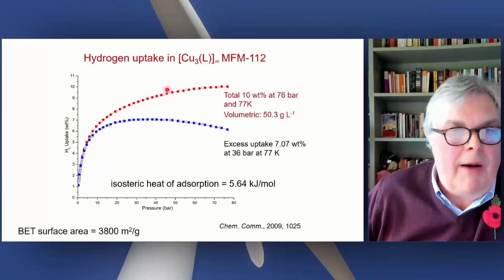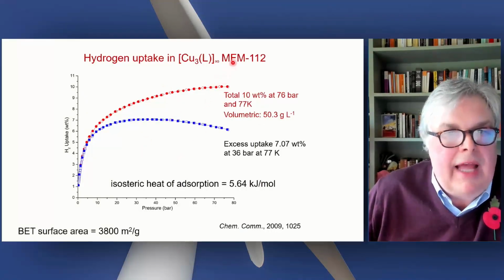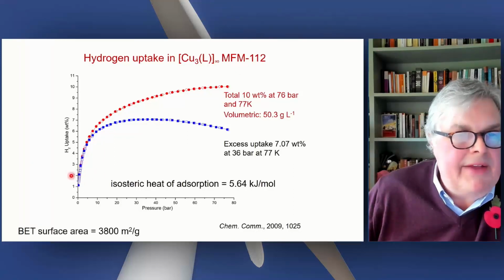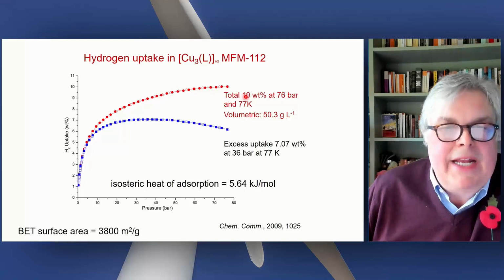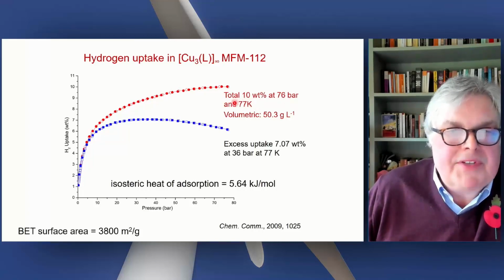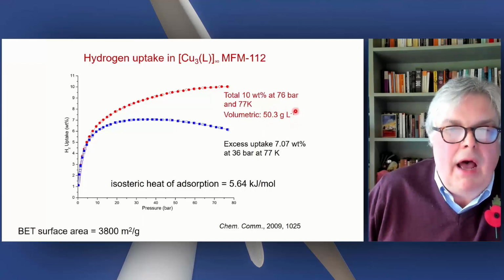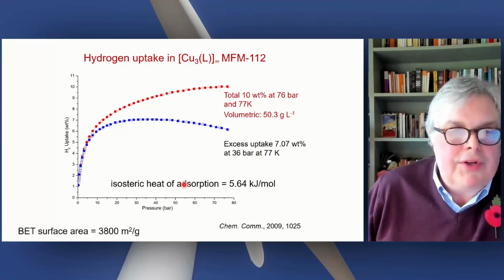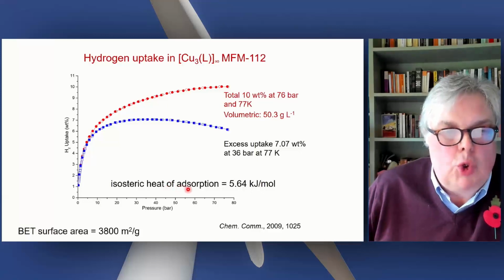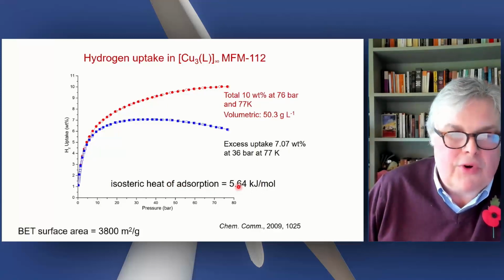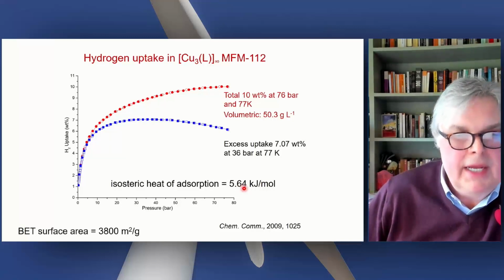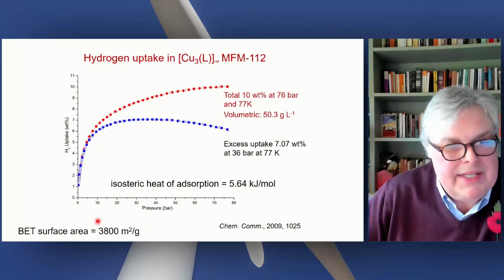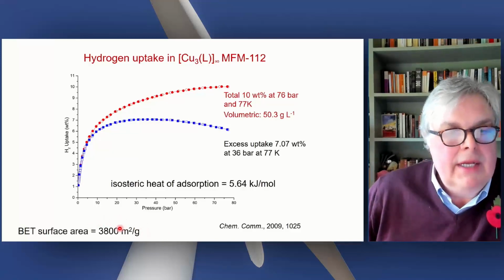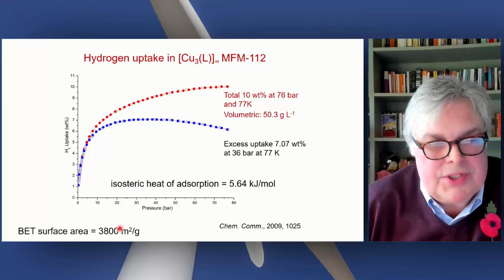And this is an example of a gas isotherm for this material, MFM-112. You can see here, this is at 0 pressure. Hydrogen is taken up to a total of 10 weight% at 76 bar. I emphasize that this is at 77 K. This is not at room temperature, but this gives a very nice high volumetric capacity. You can measure the isosteric heat of adsorption. In this particular case, it's quite low because, of course, it's a physisorption process. And a very common feature of MOFs is that they have extremely high surface area. In this case, 3,800 square meters per gram.